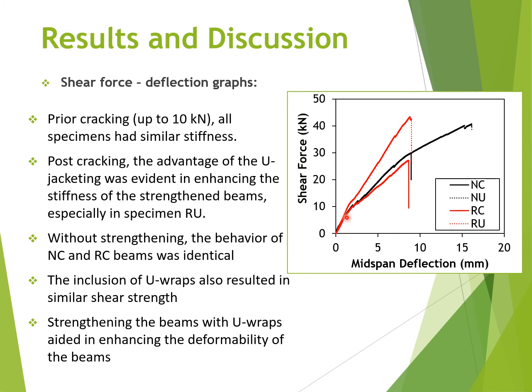Moving on to the shear force deflection graphs, we can clearly see here that prior to cracking, all specimens had similar stiffness. However, post-cracking, the advantage of the U-wraps was evident in enhancing the stiffness of the beams. We can also see that without strengthening, the behavior of NC and RC beams was almost identical, with the shear force deflection curves almost overlapping. The inclusion of the U-wraps also resulted in similar shear strength, as you can see here in specimen RU and NU. However, the specimen NU had better deformation capacity than specimen RU and failed at higher deflection.